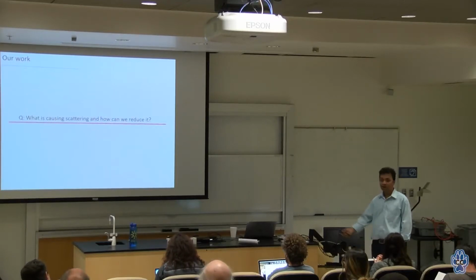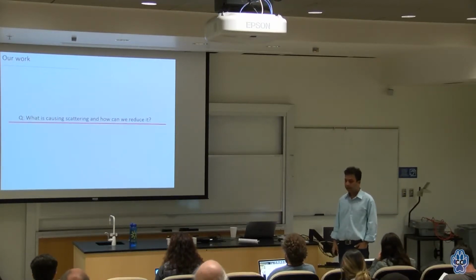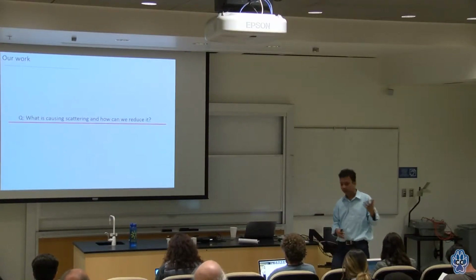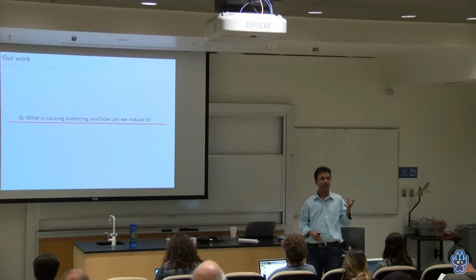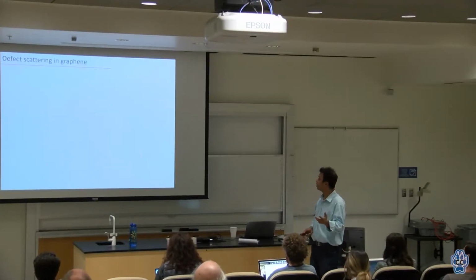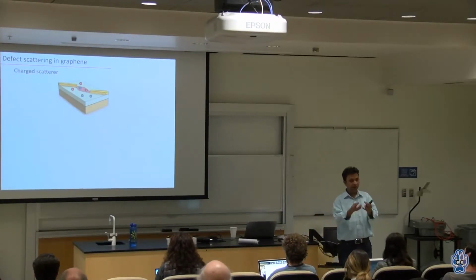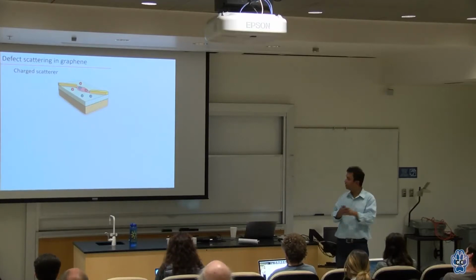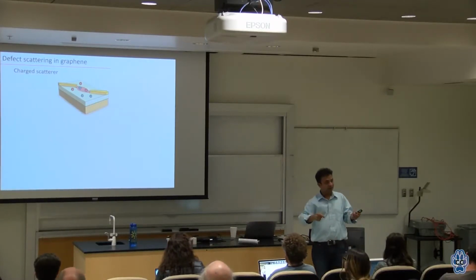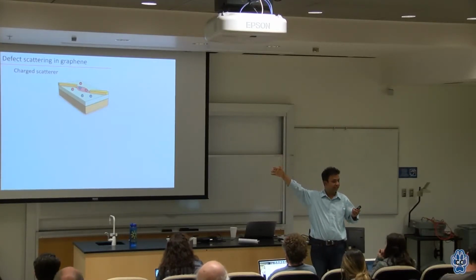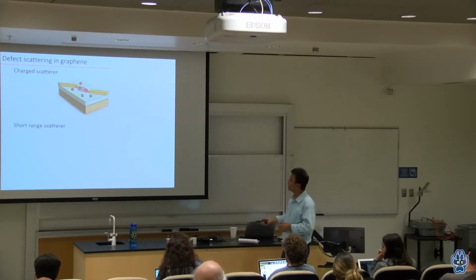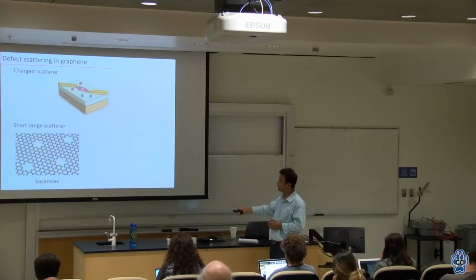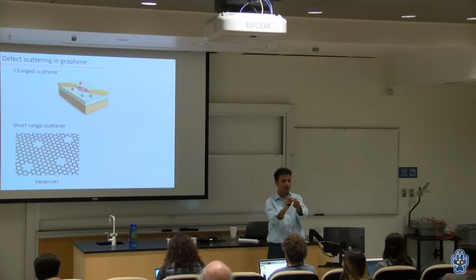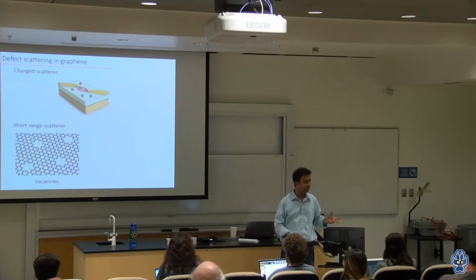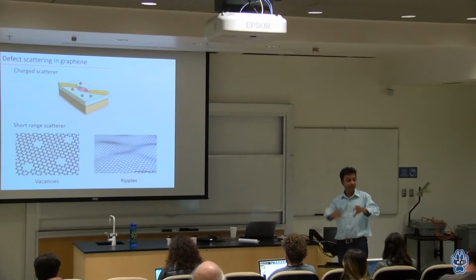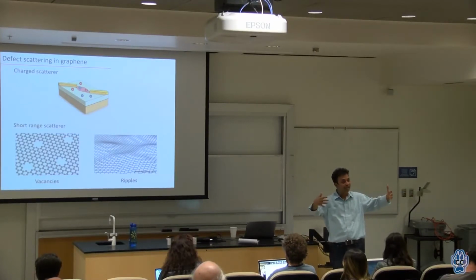Well, now I'll talk a little bit about what kind of work we do in the lab. One of the works we did at the beginning was: what is really causing the scattering in these materials? You have this flatland, and in it you will have all these charges in the system, and a charge will create what? It's Coulomb's law. Coulomb's law goes to infinity, so it's a long-range scattering. Or you can have defects in the system, such as vacancies in the graphene. That is called short-range scattering, meaning the effect does not go very far. Another one can be ripples. If you have a ripple in the system, that also introduces scattering in your system.